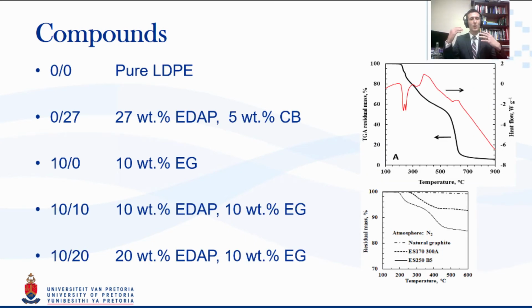The first thing we did is we wanted to identify what compounds we can test. So if we want to actually find a material that is both better than expandable graphite on its own, or the two other intumescents on their own, but also which is more economically viable or economically interesting, we would need to go to smaller loading. So we took a 10 to 10 and 10 to 20 ratio mixture of the two materials so that we could test it and find whether even at 10 to 10 loading, maybe we can succeed. And if we do, in terms of delivering the flame retardants we need, that we could use this material as a very, very viable commercial alternative.